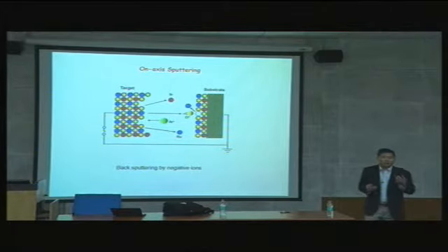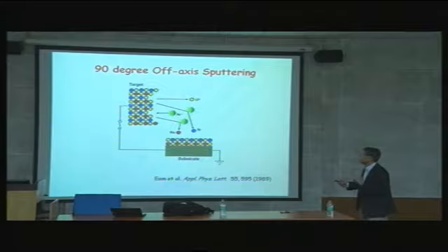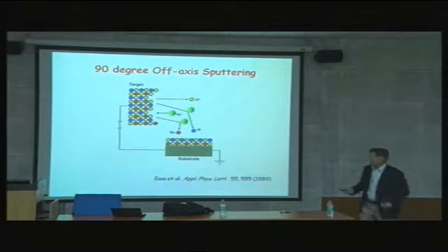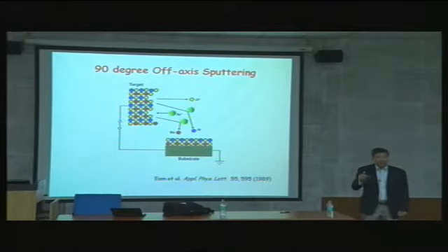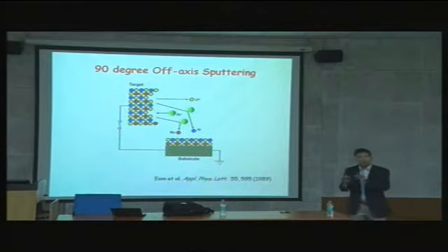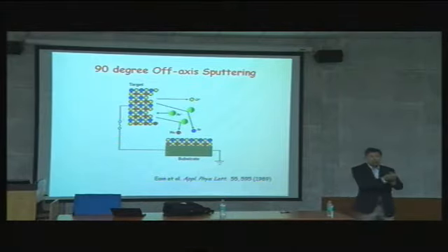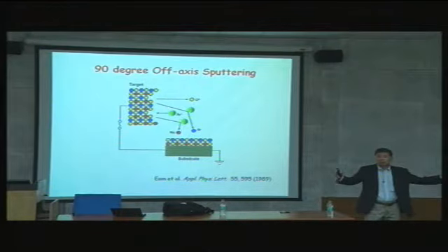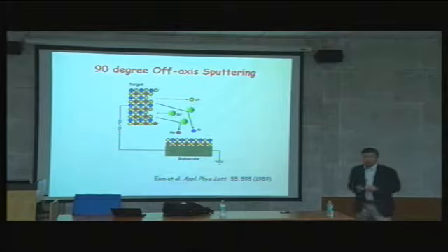So you have to use techniques that allow you to get 1-to-1. And this technique actually allows you to grow stoichiometric film of any oxide compound. Certain compounds have a more ionic nature. Yttrium barium copper oxide is one of the very ionic ones, very vulnerable to negative ions. Some oxides are less vulnerable and less susceptible to negative ions, but you have a wide range of this negative ion problem. So the simple way is, okay, let's change the geometry and solve all the stoichiometry problems.